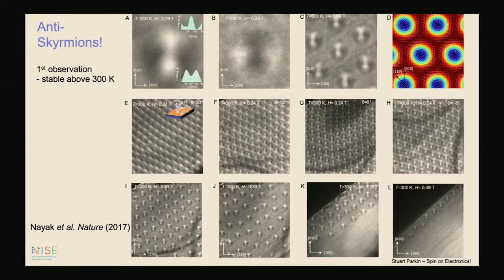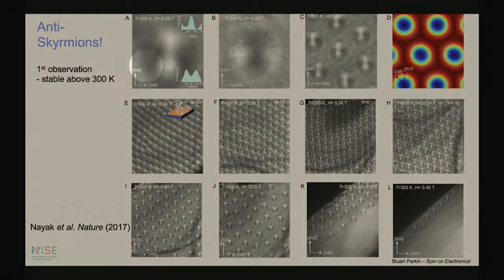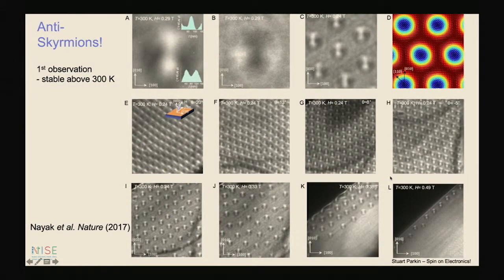And typically, when you form these anti-skyrmions, they appear in arrays like this. You can see an array of these objects, a hexagonal array. And these are different, how they look as we vary the field and temperature within the microscope. And that's what I'd like to briefly discuss. So obviously, as you increase the magnetic field, eventually you eliminate these anti-skyrmions because the magnetization all becomes parallel to the magnetic field. And that you can see here.